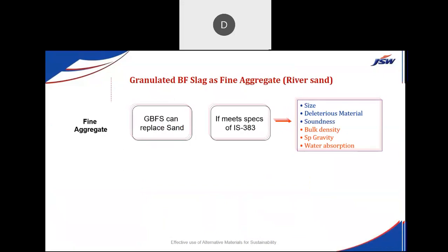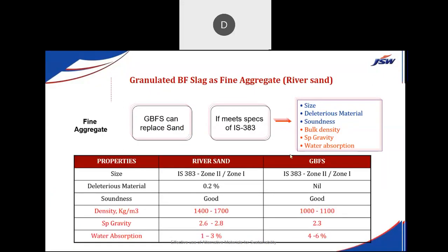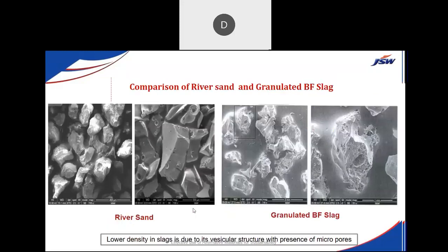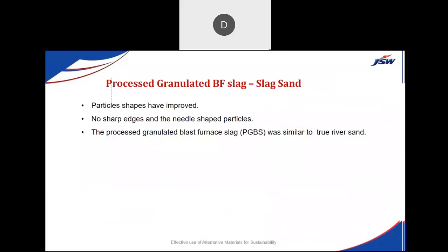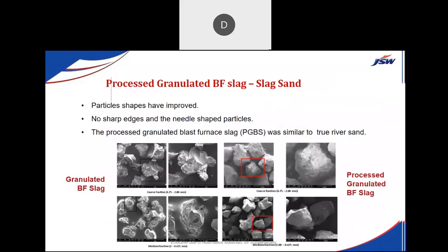So how can we satisfy the codal requirement? What we have done is the processing of the blast furnace slag, converting it into an equivalent to river sand to meet the requirement of the IS 383 code. So this was the raw material, raw granulated slag, and this is processed to get similar density like river sand, similar specific gravity, and a reduction in the water absorption. This is what the conversion using those machines we have done. So the processed granulated blast furnace slag is like a river sand, which is very eco-friendly and can also be utilized for concrete as well as plastering applications.